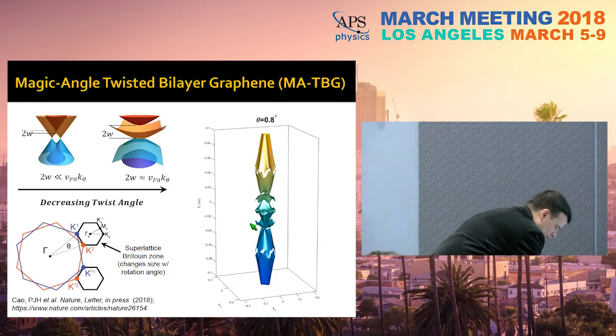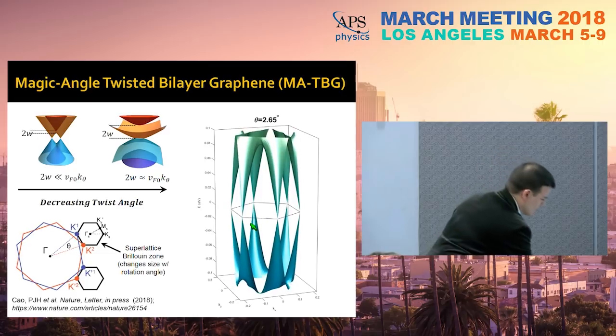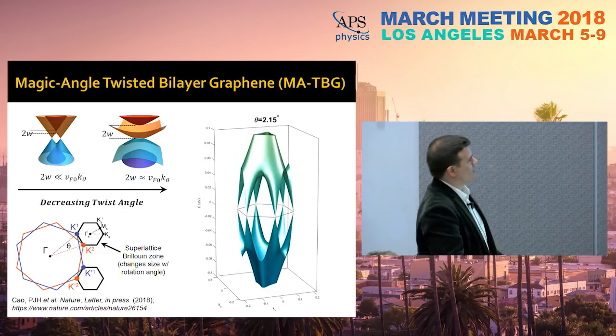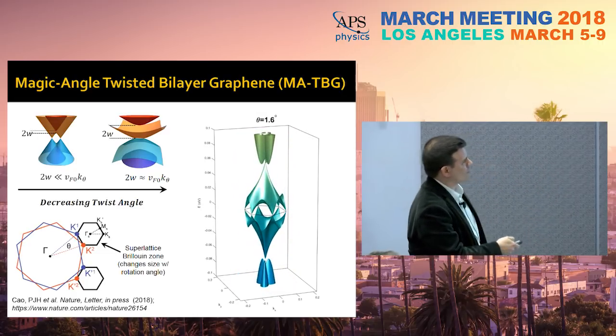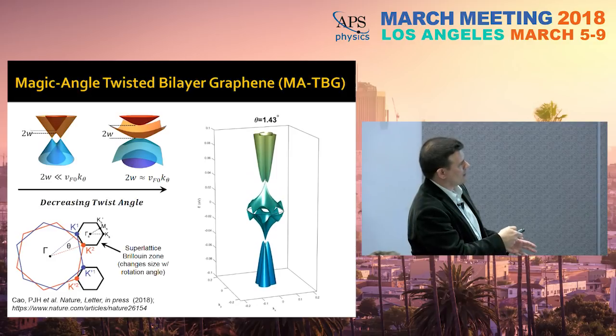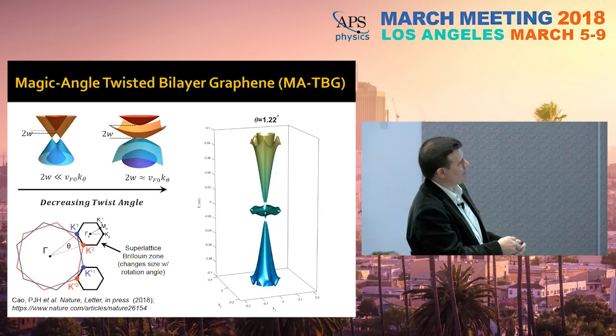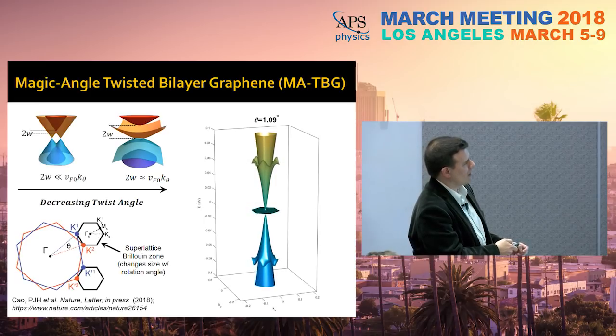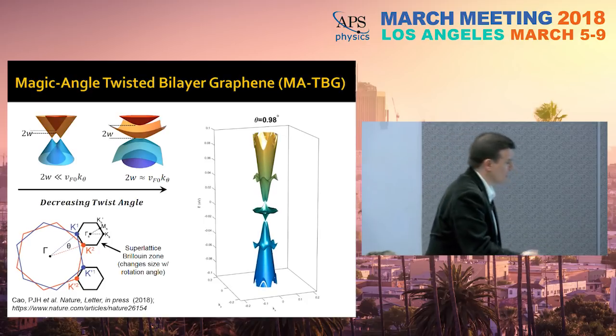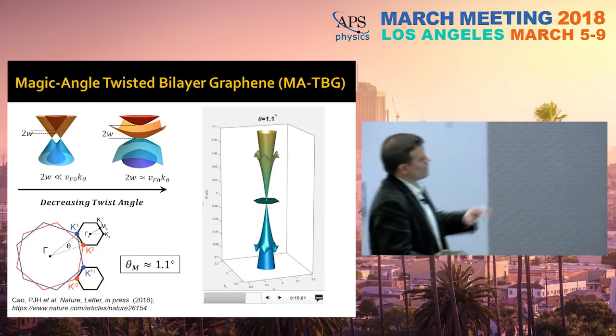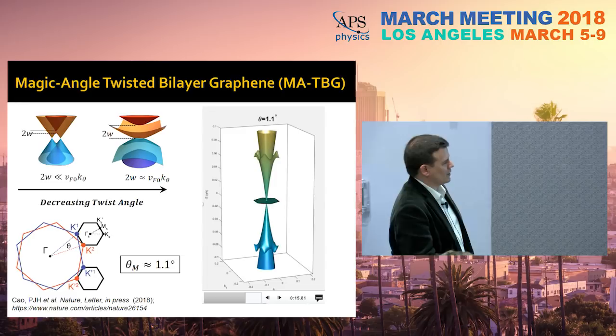Since my student put so much time into this, let me run it again. So you see there's an evolution of the band structure. The bandwidth is dramatically decreased as you are approaching the magic angle. Now you're going to get a flat pancake there at about 1.1 degrees. And then it continues evolving. So this magic angle happens at 1.1 degrees.